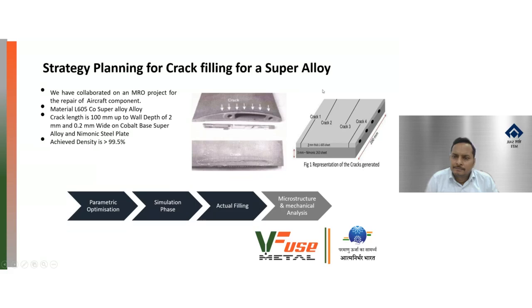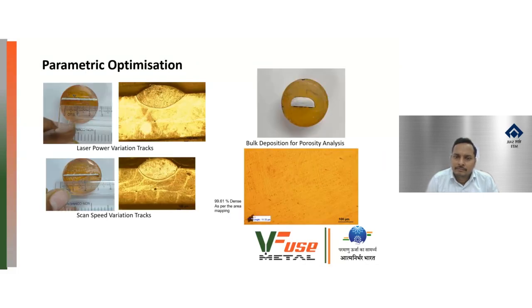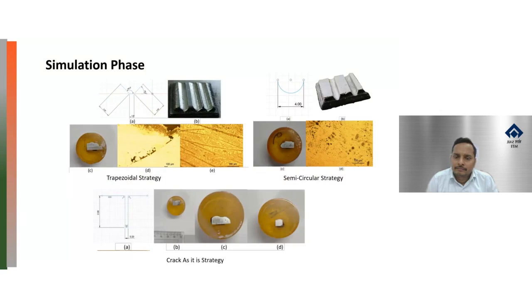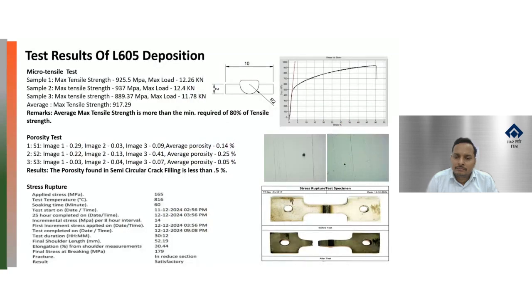We have derived a strategy. They have provided us a similar simulation plate for it, and we have derived a strategy to repair these kinds of cracks. So in this, we have grooved out the crack to a 5 thickness by 2 depth in a trapezoidal strategy and in a semicircular strategy, and we have tried it. If you do the laser welding, what will be the results for it? And we found that at the semicircular strategy, we have found the best results,